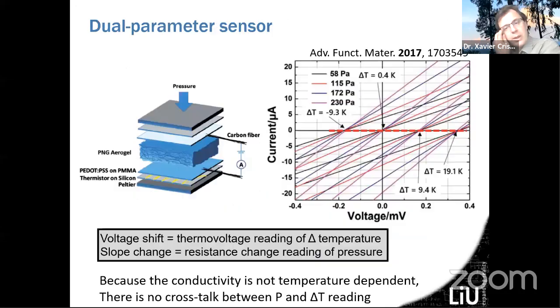And indeed, here it's what you get. These are different times, different pressures, these are different slopes, and each temperature gradient is a group of curves. Basically here is a shift. So if you have characterized your device, whatever pressure and temperature gradient you apply, you have calibrated that before, and then you can extract the pressure and temperature gradient applied. This is the concept of a dual parameter sensor.